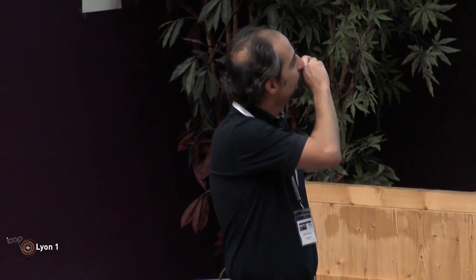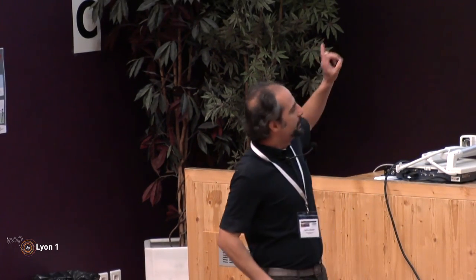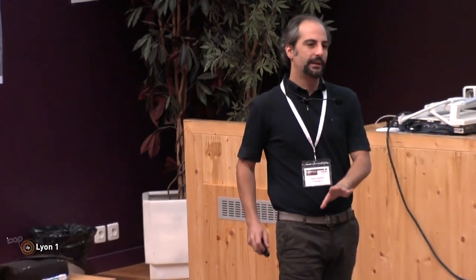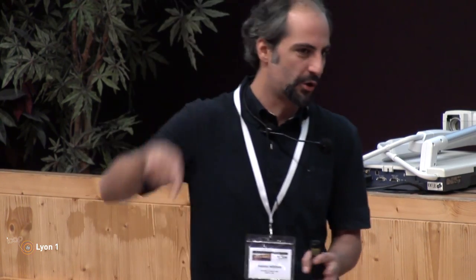Okay, so thanks for the comment. As for the questions, the first question was whether I expect this behavior to be common to other amorphous materials. When we did this work, we compared this with the literature results on other amorphous materials. There is not so much, but for instance, the behavior of silicon dioxide is completely different from silicon. In silicon, if you look at the excitonic peak in the crystalline and amorphous versions of the material, they are completely different. The amorphous peak is very much broadened with a Gaussian shape. So in that case, the structural disorder changes completely the property of the exciton.